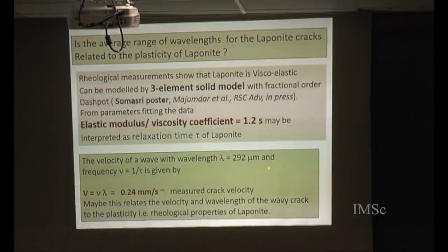the velocity of a wave with this wavelength, and if we interpret the inverse of this as a frequency, then the velocity of this wave is coming out to be 0.24 millimeters per second, which is of the order of the measured crack velocities. So maybe we can correlate these wavelengths with some characteristics of the system, that is Laponite, in this simple way.